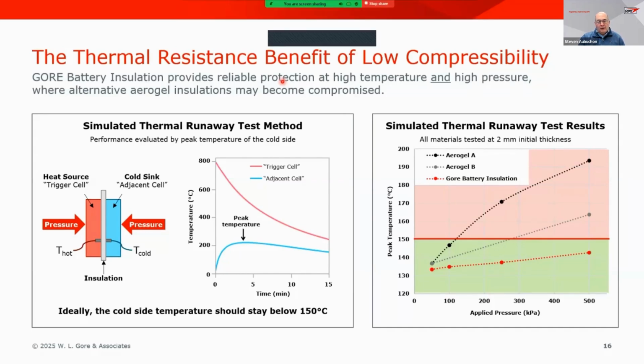So we are working, as I showed, in the test here, this was a 2 millimeter thickness. So this would have been two layers of one laminated together. So we're absolutely happy to have discussions with customers around their desired thickness and to develop strategies. But I would suggest that it's unlikely that we would produce a monolithic layer greater than 1 millimeter.